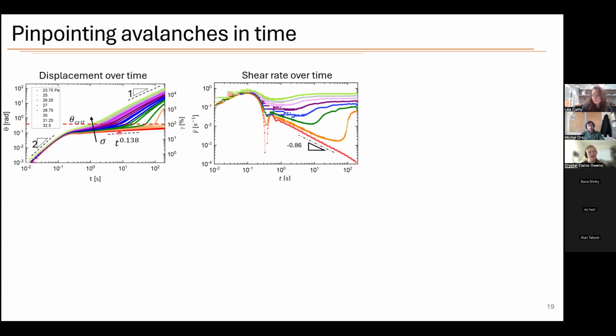This is creeping, so it looks like, oh, maybe eventually, just a little bit longer, it'll reach the critical value, and maybe the red curve will eventually flow. But it's actually a little bit longer, it can end up being like weeks if you're extrapolating on a log scale, because the material is slowing down. So it's a question of how close actually is it here. And so we want to figure out even better how to pinpoint these regions, because on this sort of plot, we see an inflection point here rather than just a transition of the slope. And so we just want to understand that better.